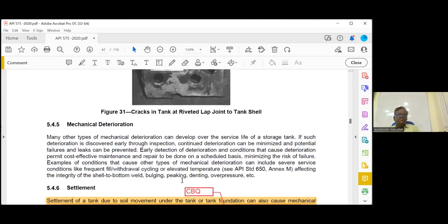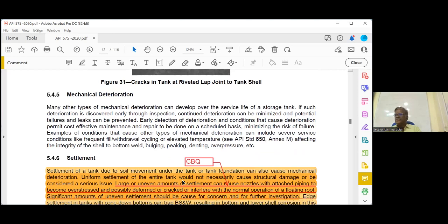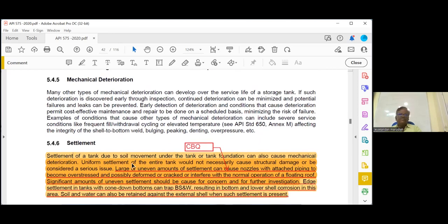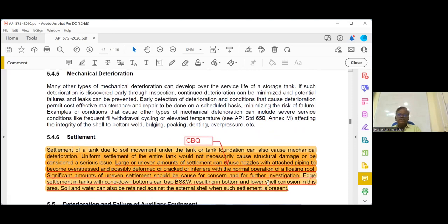Then please go to page number 5.4.6, settlement. Third line, 5.4.6. Large or uneven amount of settlement can cause a nozzle with attached piping to become overstressed and possibly deformed or cracked, or interfere with the normal operation of the floating roof. Significant amount of uneven settlement should be cause for concern and for further investigation. That line is important. Then this also highlights edge settlement in tanks with cone down bottoms can trap bottom sediment and water, resulting in bottom and lower shell corrosion in this area. Soil and water can also be retained against the external shell when such a settlement is present.